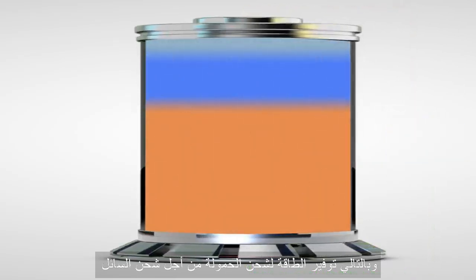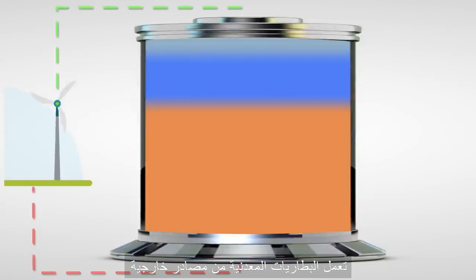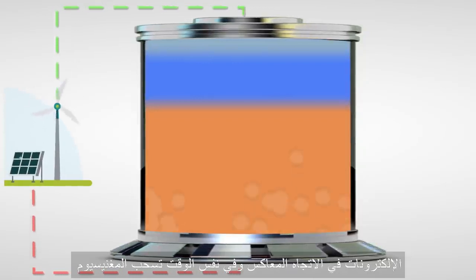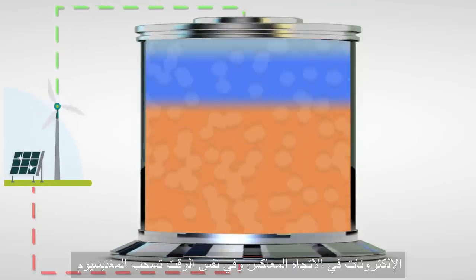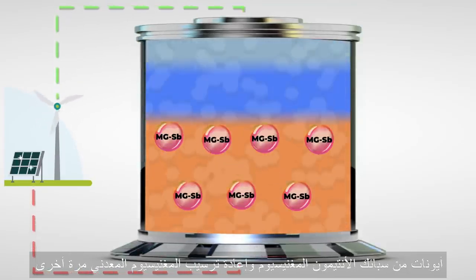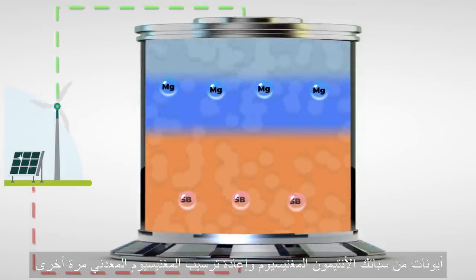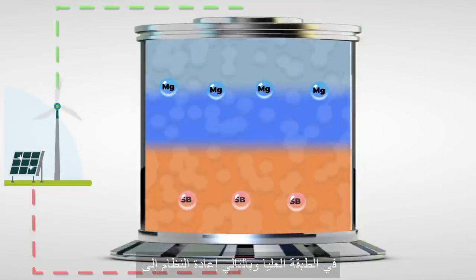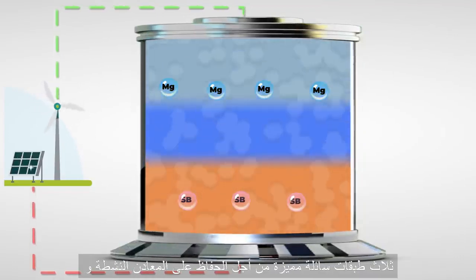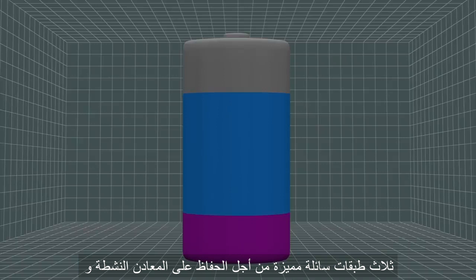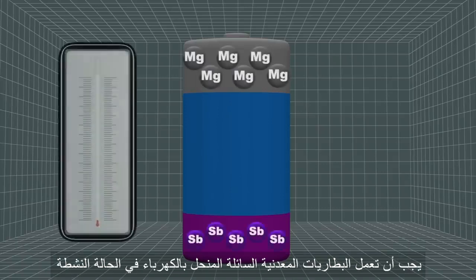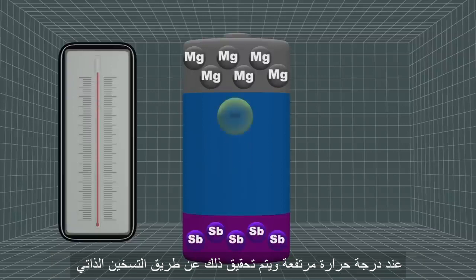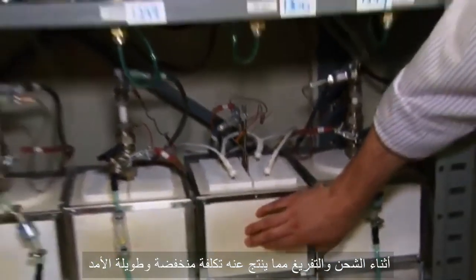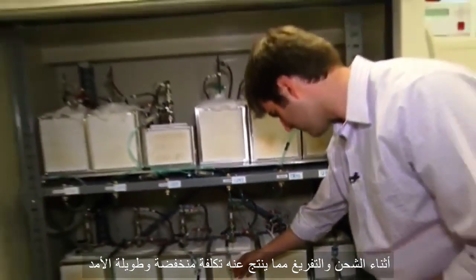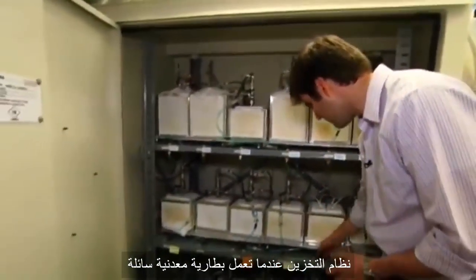Charging. In order to charge the liquid metal batteries, power from an external source drives electrons in the opposite direction, and at the same time pulls magnesium ions from the magnesium-antimony alloy and redeposits metallic magnesium back into the top layer, thereby returning the system to its three distinct liquid layers. In order to keep the active metals and electrolyte in active state, liquid metal batteries have to operate at an elevated temperature, and this is achieved by self-heating during charging and discharging, resulting in a low-cost and long-lasting storage system.